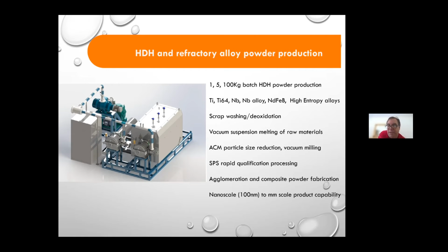So we do particle size reduction, vacuum milling, vacuum processing, all very low oxygen content, and have extensive handling of oxygen sensitive and atmospheric sensitive materials. We also have being installed 10 and 200 ton spark plasma sintering equipment that allows us to rapidly prototype equipment, and we're working with LIFT and Ohio State and others to actually develop net shape processing, rapid prototyping using these field enhanced sintering techniques. Extensive agglomeration and composite powder fabrication. We do produce feedstocks through spray drying, granulation, mechanical alloying, and others.